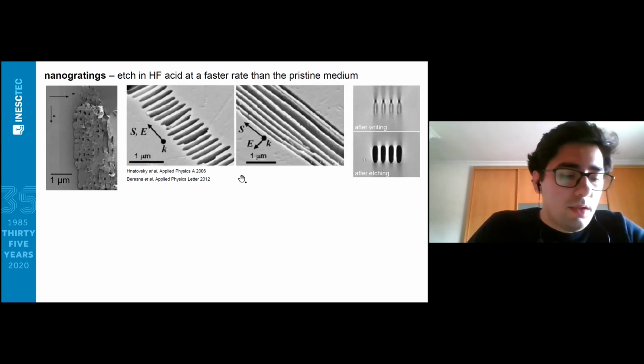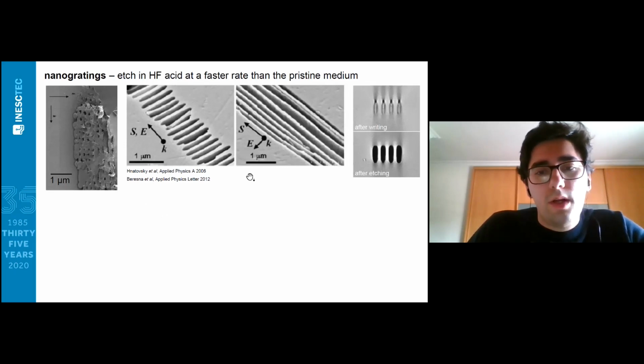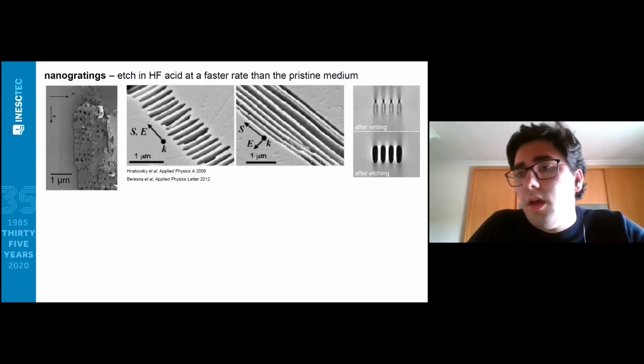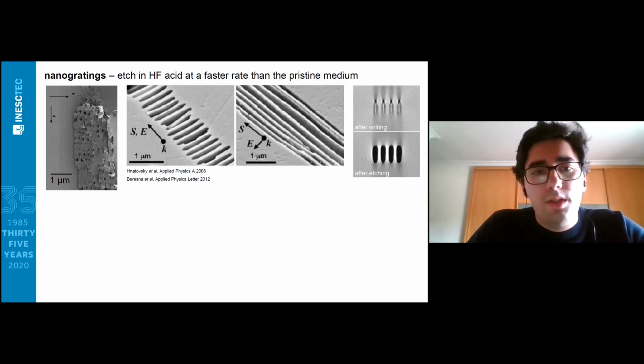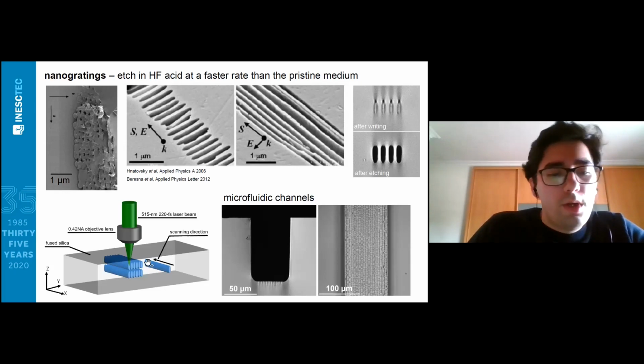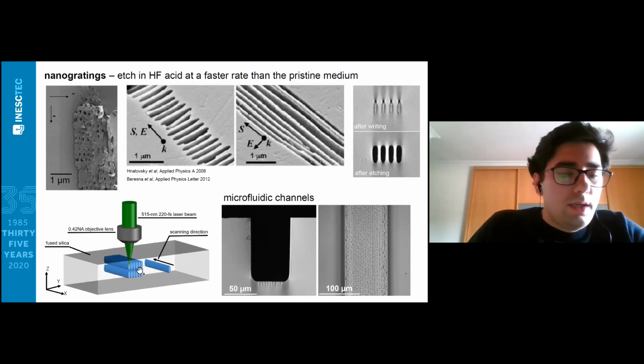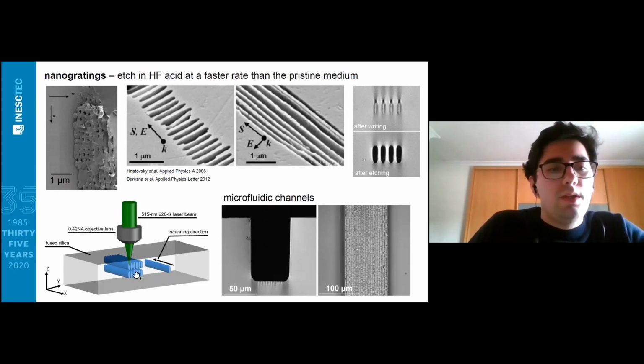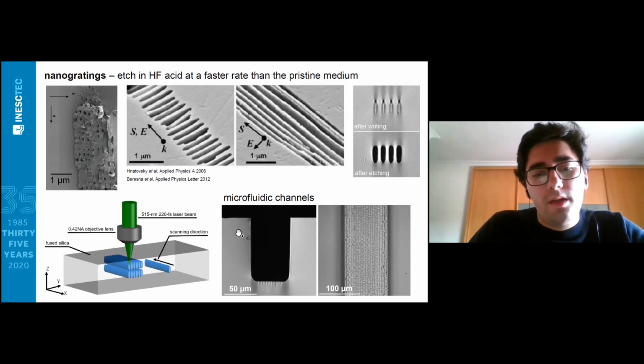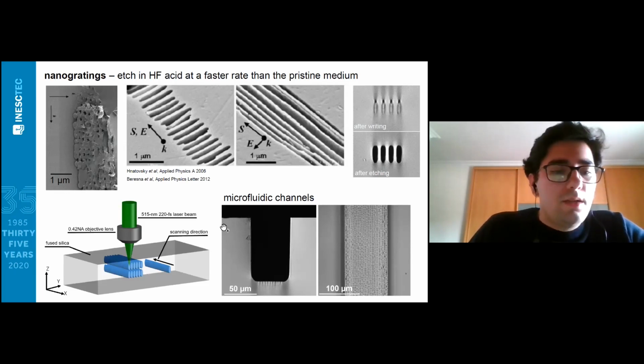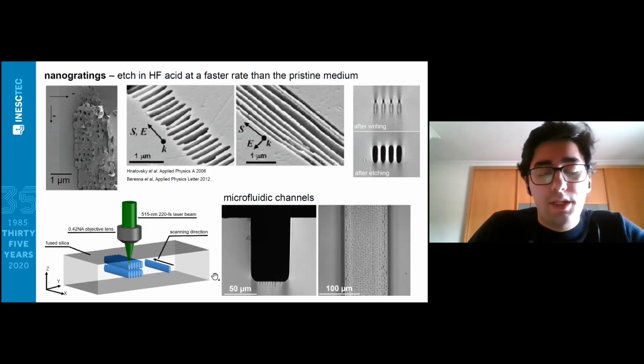So in essence, ultrafast laser inscription also allows us to generate etching selectivity where, as shown here, the laser exposure tracks are removed at a faster etch rate than the remaining material. Now if we follow a configuration where we closely stack multiple laser exposure tracks, in this case with a gap between 3 and 5 micrometers between them, and because this modification also shows long range order, we can form microfluidic channels with any size, and by changing the way we stack these tracks, with any shape as well.